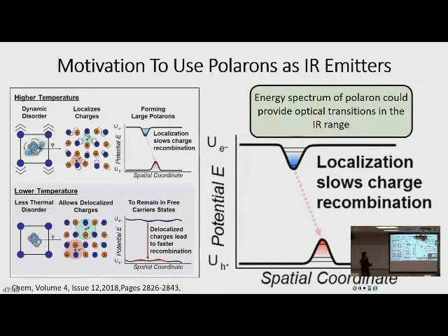I see what you're saying. So excitons screened by atomic motion. Please correct me if I'm wrong. In the perovskite community, people believe that excitonic effects are very small and negligible because the dielectric constant is around 1000. Second, polarons can be created by optical excitation, but it's not necessarily the case that positive and negative polarons exist simultaneously. You can inject charge and create only negative or only positive polarons separately. Oh, okay. So polarons exist even without optical excitation.